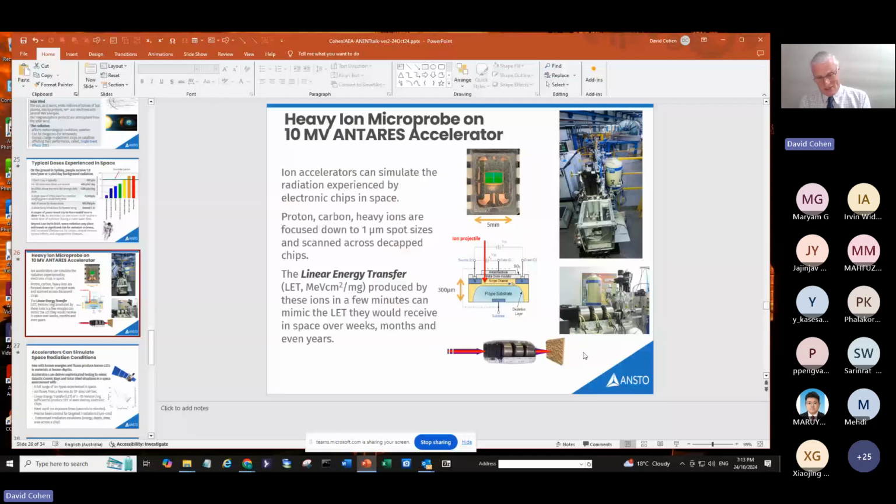It's exactly the same as X-ray fluorescence, except instead of exciting the X-rays with X-rays, we excite them with ion beams, protons or helium beams, for instance. So a different energy? Yeah, it's the energy of the proton. The other thing is that the background you get is called secondary electron Bremsstrahlung background. It comes from secondary electrons. It's much lower for protons because the proton mass is 1836 times more than the electron mass. And so you get much lower backgrounds with proton-induced X-rays than you do with XRF, or X-ray-induced X-rays. Yes, thank you very much.